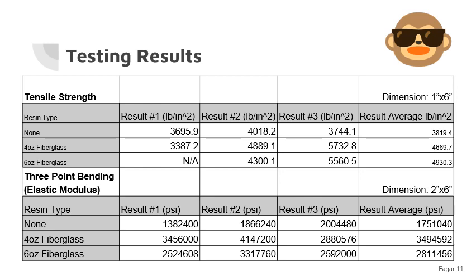For the 3-point bending, the result average PSI for the bare board was almost 2 million PSI, which is also in the range that we were expecting. And it did steadily increase for the 4-ounce fiberglass, and then we got strange values for the 6-ounce fiberglass, which could be due to the variability in our wet layup and issues with the resin. I'm going to hand it over to Jensen.